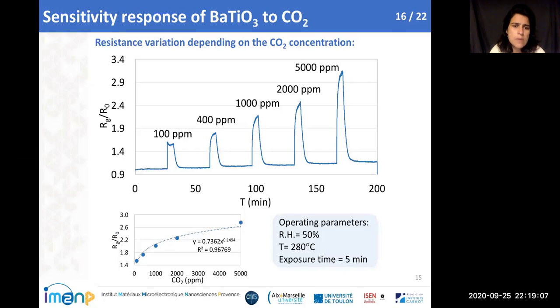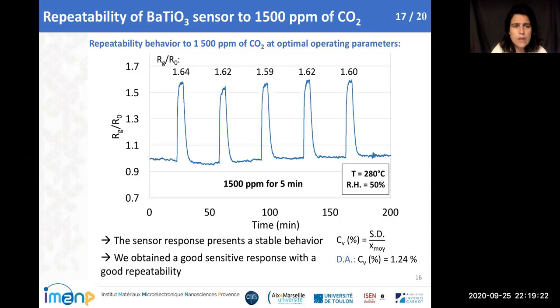Here, this is the response versus the concentration of carbon dioxide. We have an increase of the response when we increase the concentration. And here it was for an exposure time of 5 minutes. We also study the repeatability of the sensor for 1,500 ppm of carbon dioxide. And we have here a good sensitive response with a good repeatability, with a coefficient equal to 1.24%.